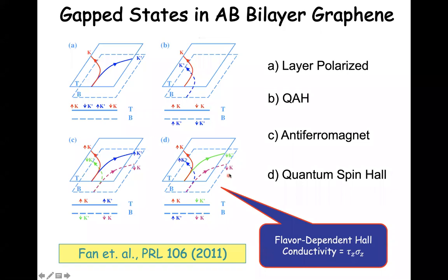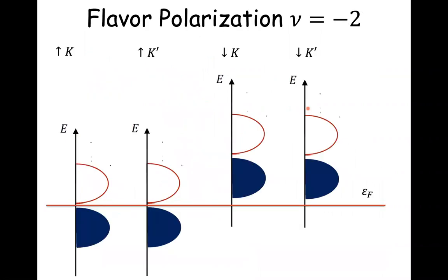The ground state, it turns out, is actually an antiferromagnet, state C here. But what you see in experiment is that this state, where you have a quantum anomalous Hall effect, even though it's not the ground state, appears if you apply a little magnetic field to stabilize it. And all of these things occur also in twisted bilayer graphene, but you don't have to remove the dielectric, so it's much easier to get at experimentally.